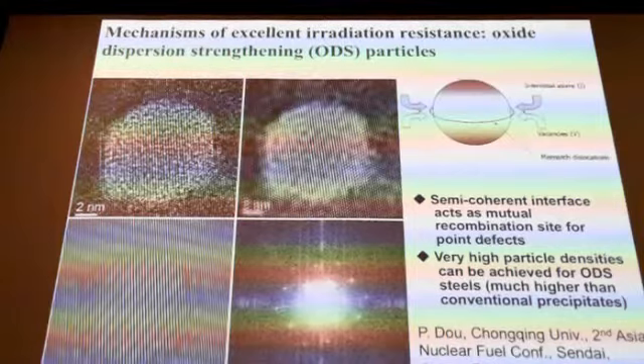And again, the process for the recombination is, this is an example high resolution image of an ODS, oxide dispersion strengthened particle. A defect that's migrating through will come in and be trapped along the surface of this particle, and then a little bit later in time, a vacancy can come along, and this just acts as a collection center for the defect and anti-defect to show up. Then as they're migrating around that surface, they'll eventually find each other and recombine.